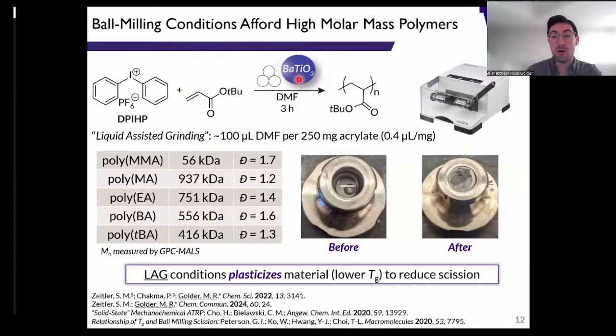But the real take-home point of this slide is that in addition to the increased viscosity and the presumed decreased rate of chain termination, we think that in addition to the DMF acting as a reaction medium for this reaction to proceed, we also think that it's plasticizing the material along the way. And it's lowering the glass transition temperature, and that reduces the rate of chain fission. And this is work that was all outlined by Peterson and Choi a few years ago in this nice Macromolecules paper that correlates a particular polymer's glass transition temperature to the rate of chain fission.